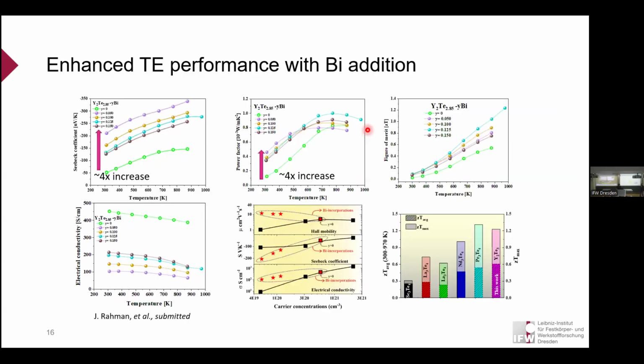Charge carriers are already in the level, I would say 10 to the 20 something like. But what would be a perfect material? A material that is very conductive at the grain boundaries. And which parameters should I think are really best for thermoelectric? It should have a low charge carrier concentration, but with a very small amount of defects. Lower charge carrier, yeah, lower charge because we have higher mobility,